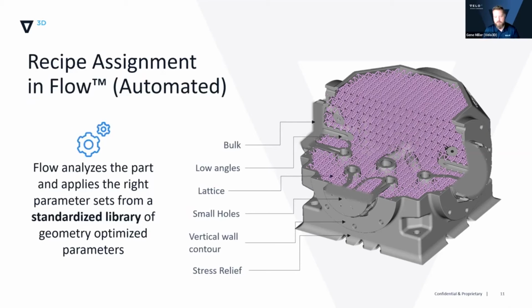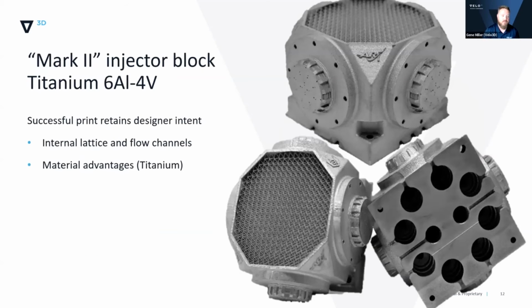So how do we do this unique printing? We have built a preprint software where we have the ability to detect geometric features, such as bulk, low angles, and lattice, and apply a specific laser parameter to print these geometries without the need for support material in most of the cases. So this is all done automatically by the software. The user does not have to be cognizant of these process applications. And this is what you see here, the part that we printed in solid titanium with the very lightweight lattice structure on the inside.